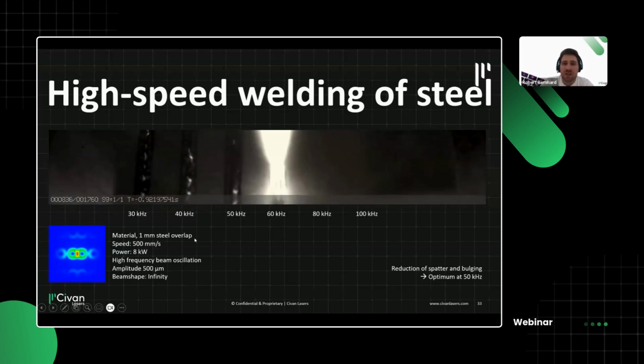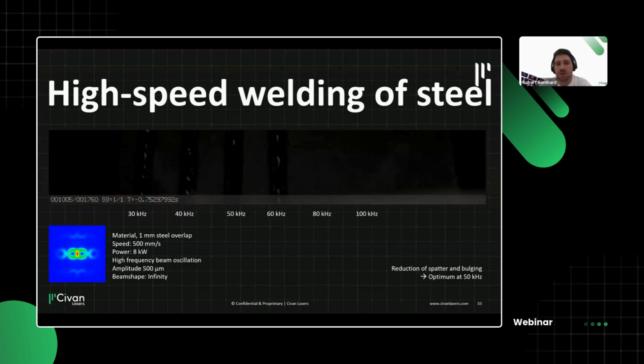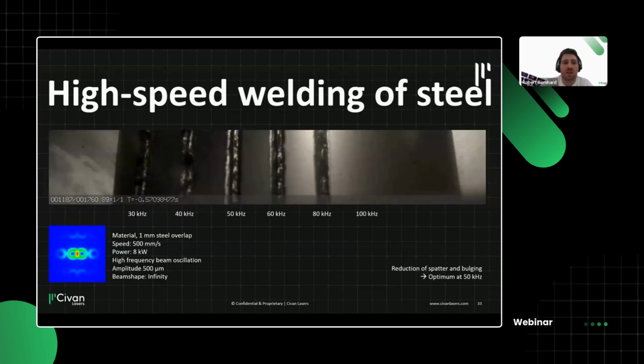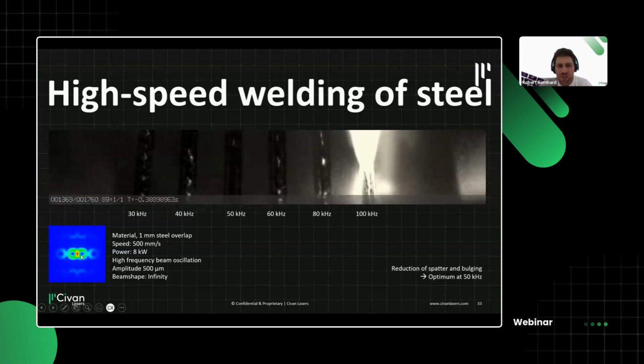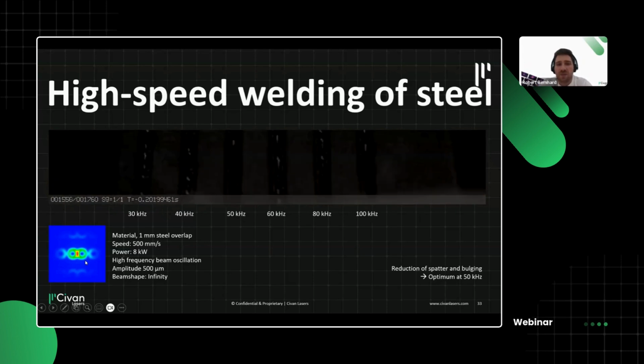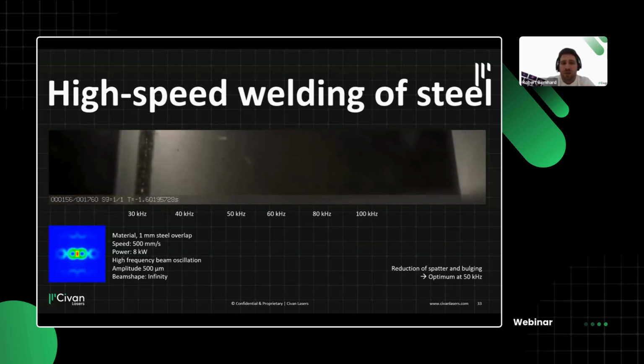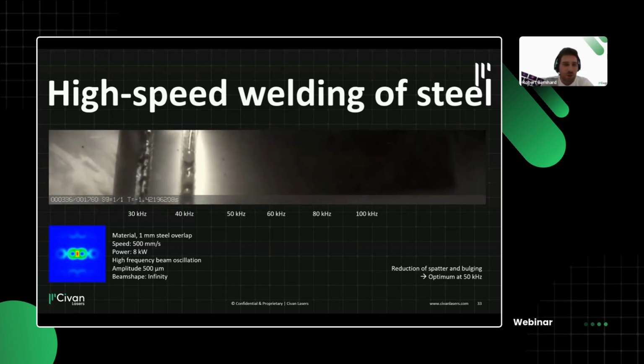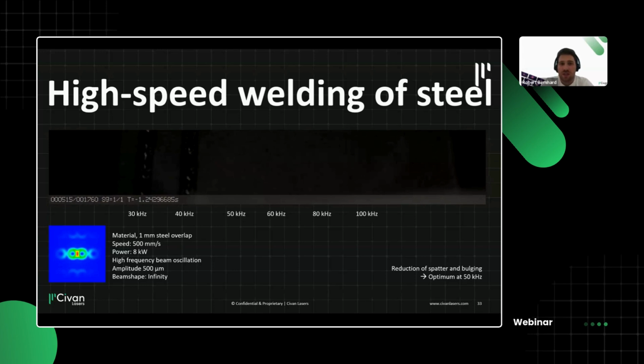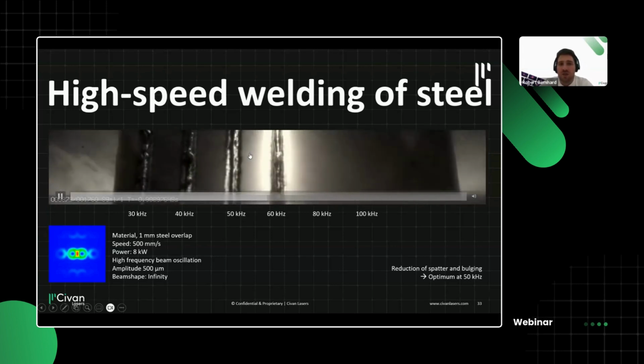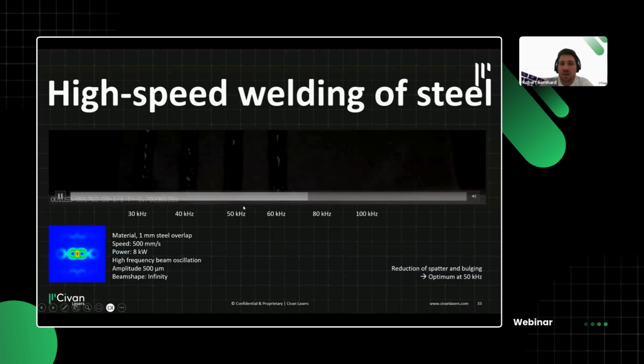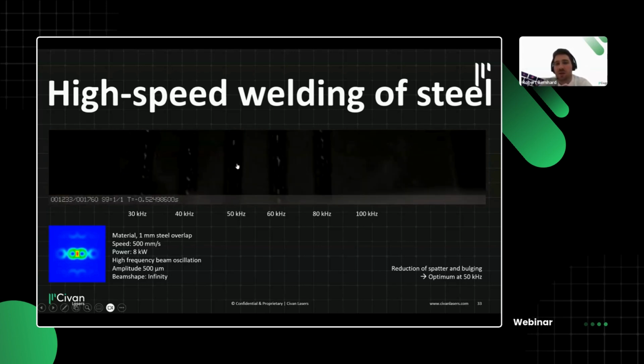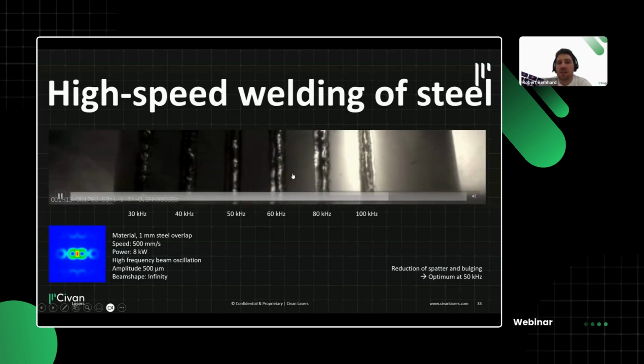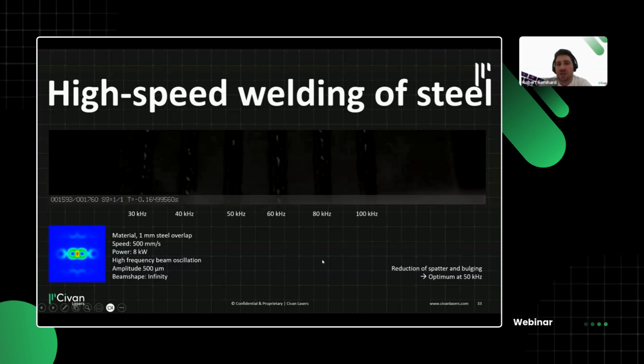And what we found here is that when you look at this video from left to right, we increased the shape frequency. The shape here was something like an infinity wobble pattern, but doing this wobble pattern at frequencies of 30 to 100 kilohertz is way faster than any mechanical scanner can do. And you see that you start with a lot of spatter at the high speed, but then you finally end up at a sweet spot of 50 kilohertz where there's no bulging, almost no spatter, and then the bulging at higher frequencies comes back.